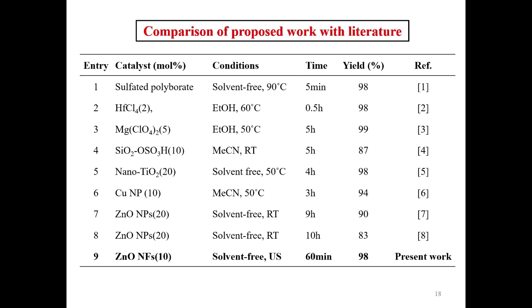Comparison of the proposed work with the literature available here. So different catalysts: sulfated polyborate, HfCl4, Mg(ClO4)2, SiO2-SO3H, nano TiO2 is also used, copper nanoparticles, zinc oxide nanoparticles, and this is the zinc oxide nanoflowers. Only 10 mole percent is required under solvent-free condition. Only 60 minutes is required. So the yield is 98% as compared to the others.